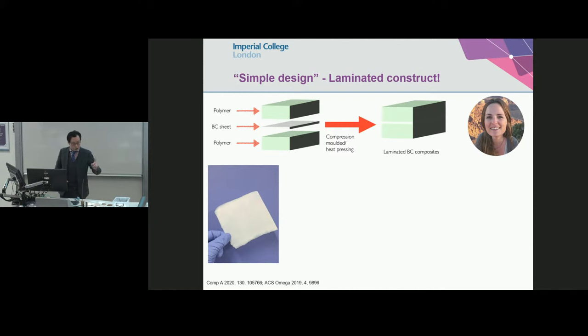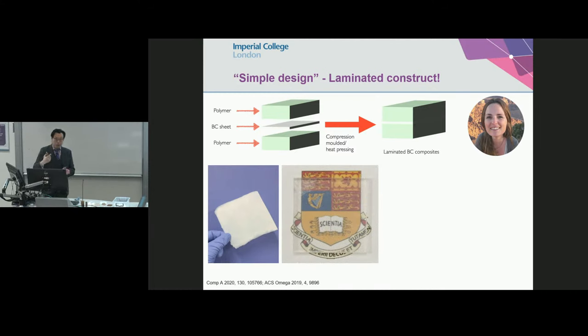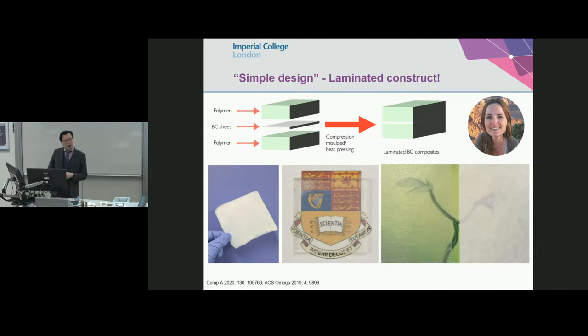So we started off with the dried version of that bacterial cellulose, which basically is this thing right here. Well, you can dry that, it becomes this little tiny piece of paper. You put them in a polymer, it actually comes up transparent. For the reasons that I told you earlier. So that small fibril diameter and the matching refractive index, and it actually works. But what Alba did actually find out was that if you do it wrong, it will not work. So this picture on the left here actually showed that if you have this wet pellicle, wet cellulose, when you press them directly into a dried sheet, when immersed in a polymer resin, it's transparent. It's great for us.